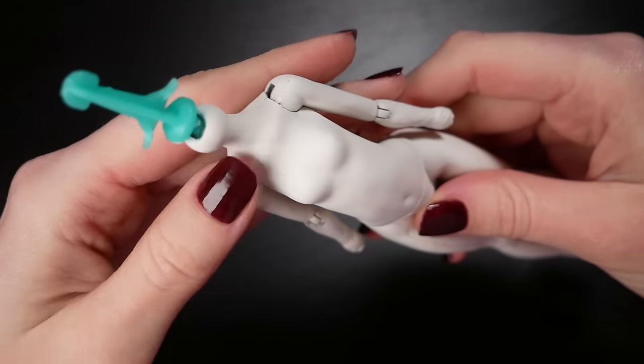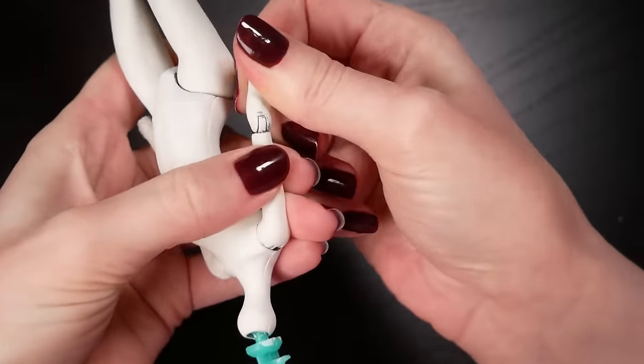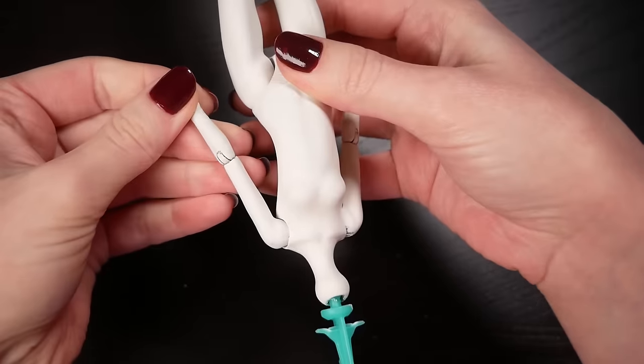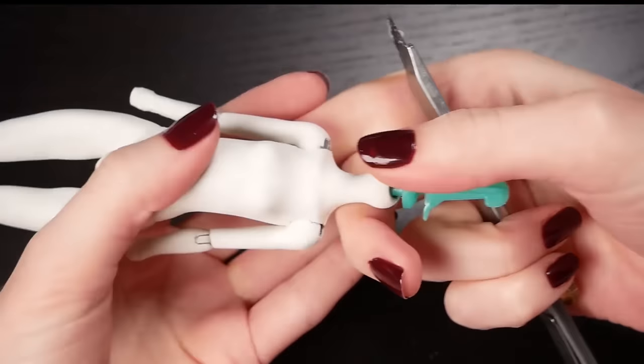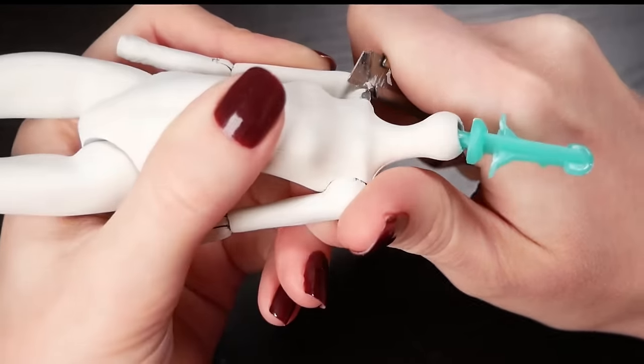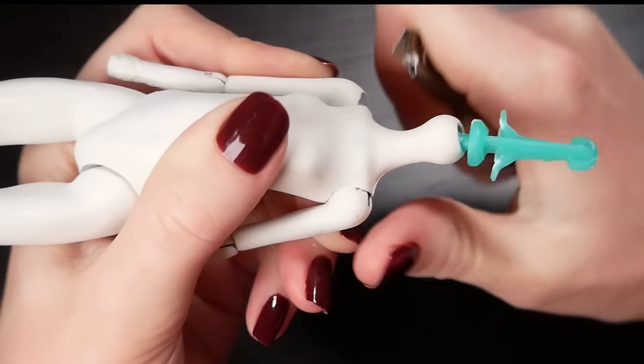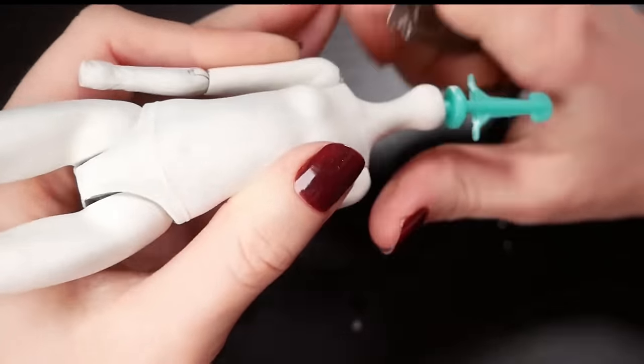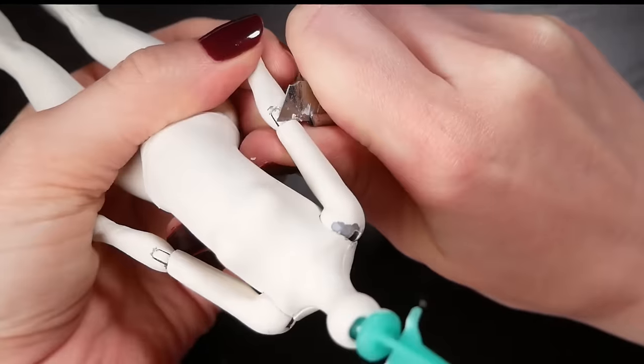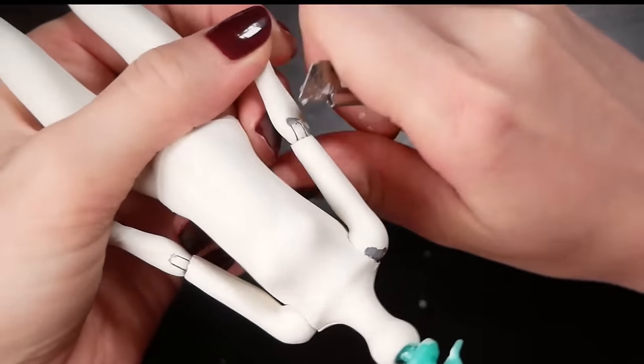It definitely sticks way better than acrylic paint, and on all of the dolls I painted with it before, the joints are still intact. However, with this doll I had problems. At first I thought it happened because I had to switch to another brand, which is partly true, but when I used this paint on my Yuki Onna doll, for example, nothing chipped off. So I think in this particular case the doll just had very tight joints, and even without paint there was already a lot of friction going on, and an additional layer of paint couldn't survive it.